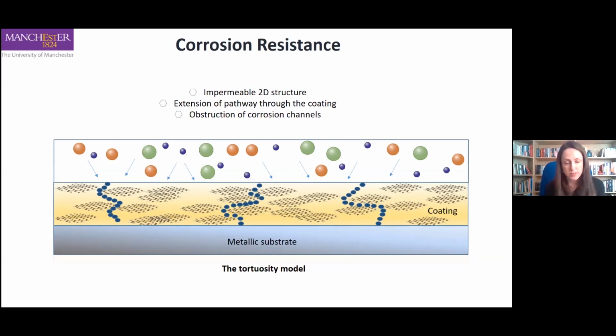Also, when you apply a coating, when you process it, when you use an application procedure, when you cure it, you can get defects within a coating. Obviously, you can get micropores, nanopores, and it's suggested that because of the surface area of the graphene and that layered structure, you can actually block the pores of the defects in the coating as well, and that also helps to block routes down to the metal below, which would be there in a normal coating.